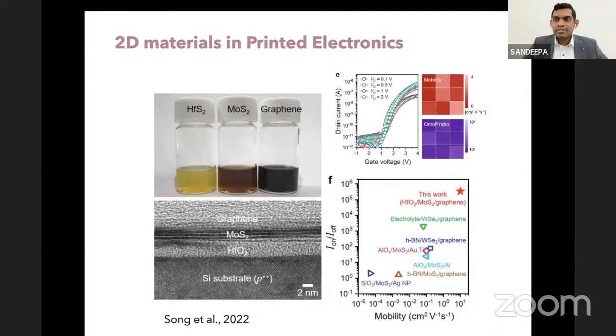However, one of the drawbacks of printed electronics is that here we are dealing mostly with polymers, sometimes 2D materials. Polymers are the most common in printed electronics, but compared to polymers, 2D materials show very long life and durability. Therefore, 2D materials are getting more attention in printed electronics in the current world. Otherwise, people are more focused on polymeric materials. However, for electrical properties, transistors based on 2D materials and printed electronics can achieve around 10 to the power 6. In silicon, we are thinking about 10 to the power 8. That's the minimum standard we are looking for. But for certain applications like sensors, we still have a manageable level of on-off current using this technique. Most printed materials, depending on the quality, can achieve an on-off ratio of 4 to 6 orders of magnitude using printed electronics.